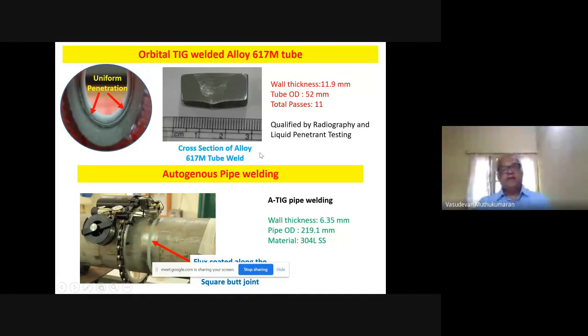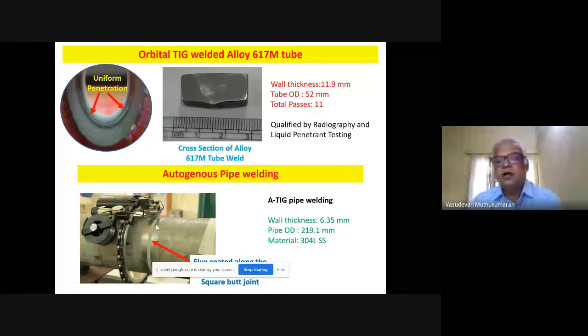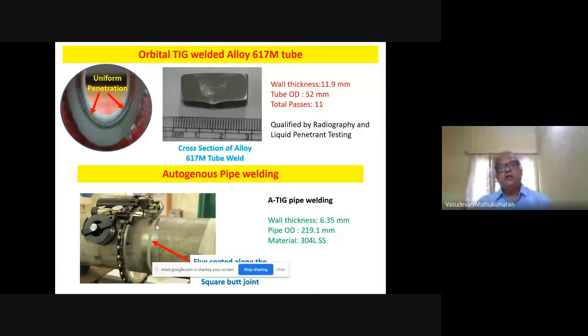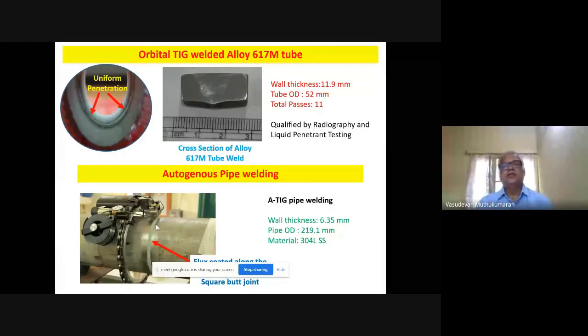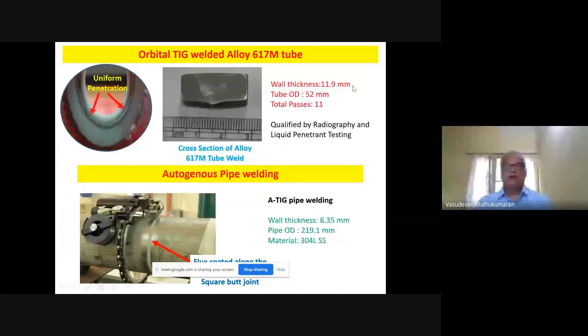Then again we use the same system for TIG welding of 304L pipes. We are successful in using our orbital TIG welding. Here the torch moves around on the track to weld these. This wall thickness is 6.35 mm, OD is 219 mm. Material is 304 stainless steel. So we could use all this orbital TIG. It's also an automated process. We could control everything and we could fabricate defect-free components successfully.